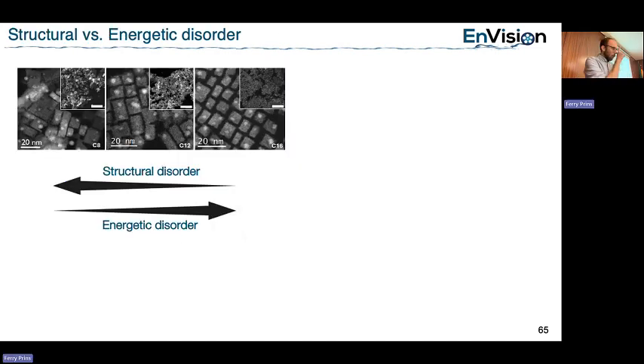Okay, so now we have two things. On the one hand, I have structural disorder because the morphology of this film is really bad - a lot of different sizes and they don't pack well. Here I have better packing and better size distribution, so less structural disorder. But my energetic disorder apparently is bigger here than it is there.